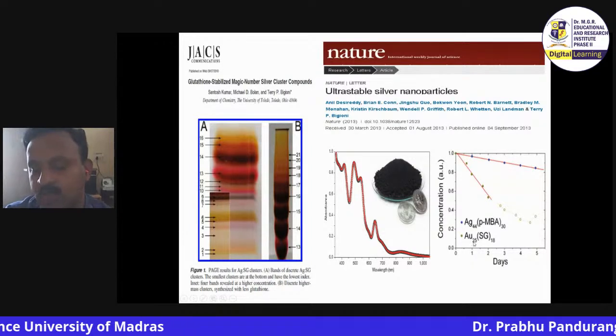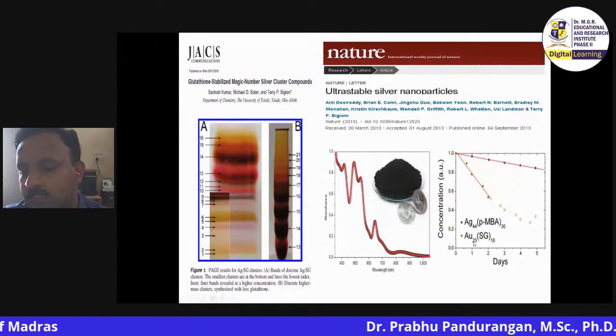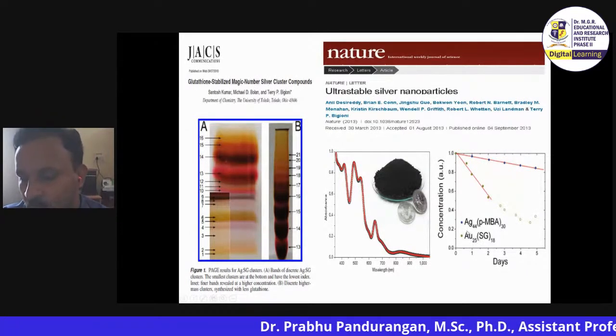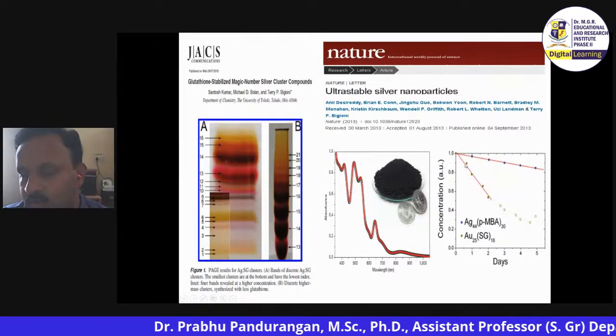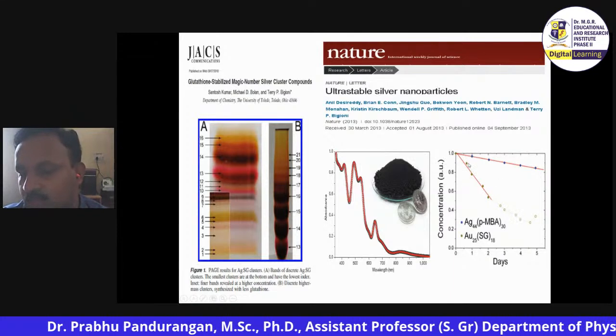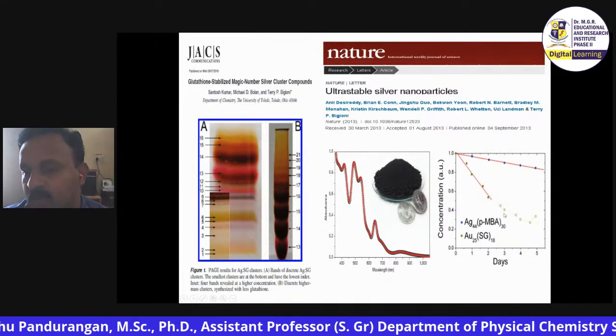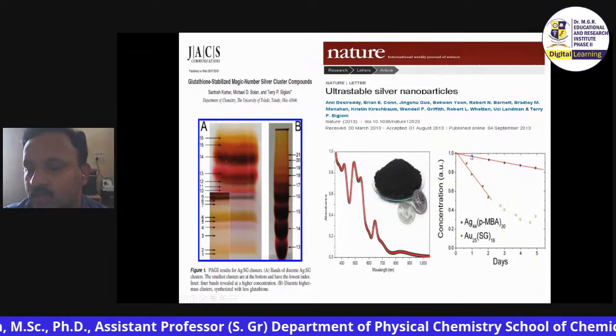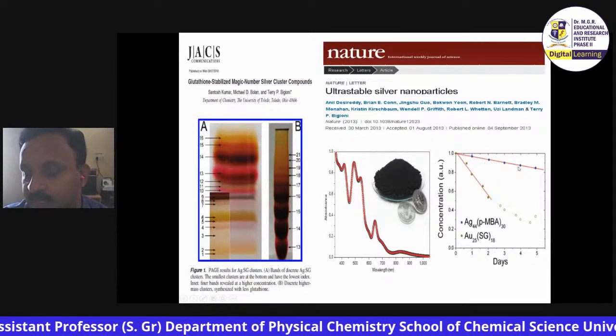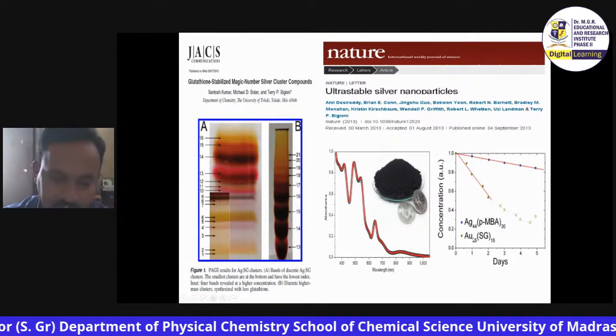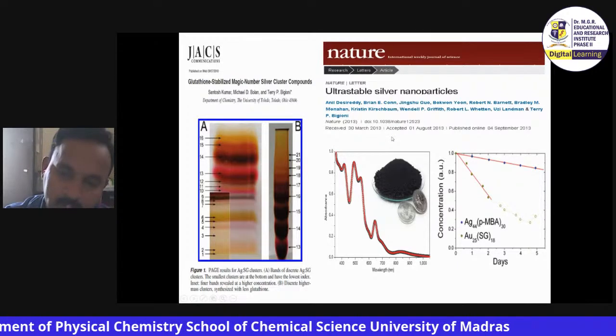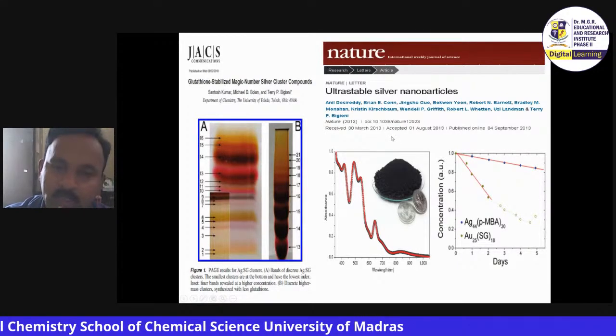Gold is so far considered to be highly inert, highly stable, but you can see in this paper, gold 25 is the yellow dots shown here, which has a drop in stability concentration, whereas silver 44 is able to have better stability as compared to gold 25. So that's why this paper has been published in Nature.